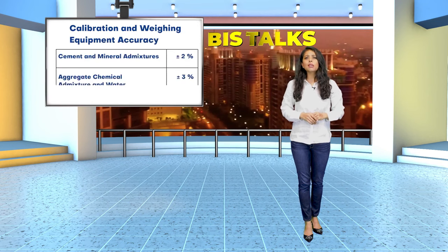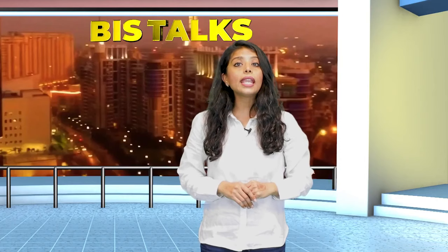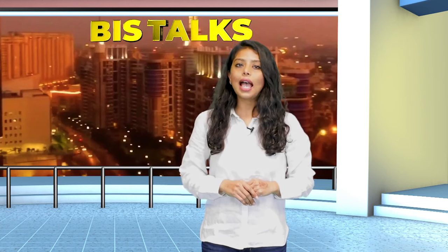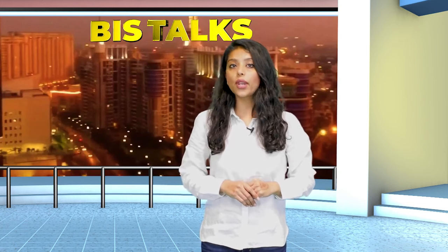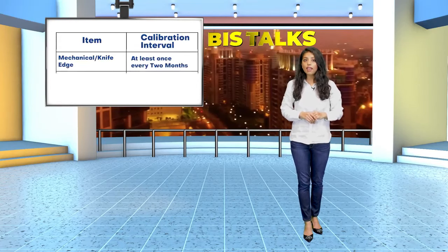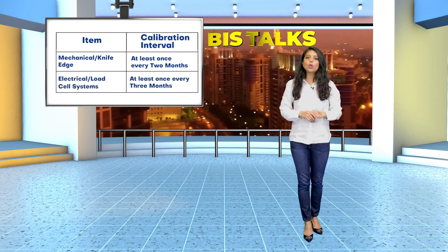For cement and mineral admixtures, plus or minus 2%; aggregate, chemical admixture and water, plus or minus 3%. All weighing and measuring equipment are tested and calibrated over their full working range. Mechanical or knife edge systems are calibrated at least once every 2 months. Electrical or load cell systems are calibrated at least every 3 months. Continuous weighing systems are checked using preset quantities with those actually produced. Calibration of weighing equipment is done by competent and trained personnel.